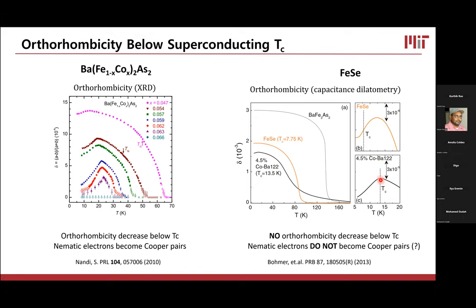So there's a feature in the thermal expansion that hits right as Tc hits. On the iron selenide side, though, there really isn't a clear feature at the onset of superconductivity. And it should be noted that the scale of this is 10 times zoomed in compared to this scale. So there's really only a very subtle change that's happening in this temperature range. And there's nothing specific that's happening at Tc itself. And there's not a clear suppression of orthorhombicity due to the onset of superconductivity. And that leads to this idea that maybe nematicity in iron selenide isn't directly in competition with the superconducting order. It could potentially even be cooperating with the superconducting order.